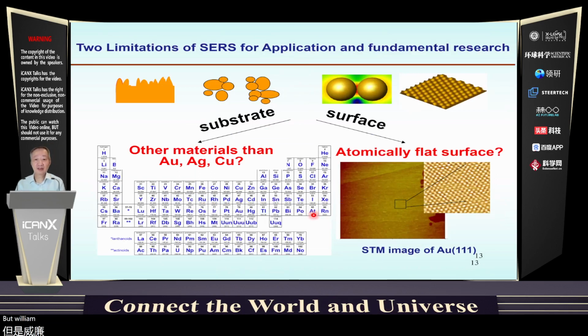But very unfortunately, in the early 1980s and all through the 1980s, people gradually realized that the SERS-active materials are limited to gold, silver, and copper. And moreover, the surface science community also did not accept SERS. They complained that for structurally well-defined single crystals, SERS cannot be used for their theoretical modeling studies and simulations.